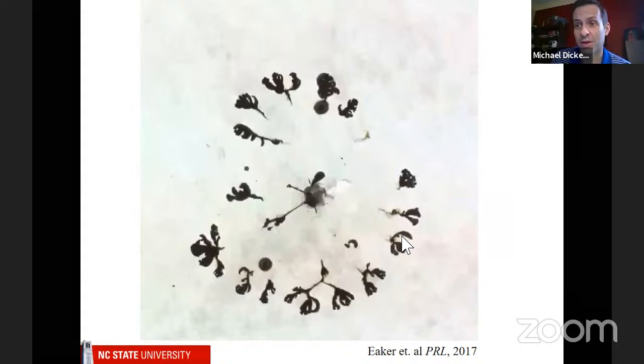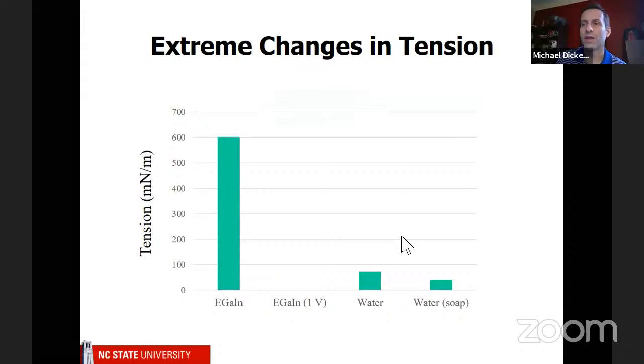So the implication here is we're lowering the surface tension very, very low. And to give you an appreciation for this, because again, I don't think most students think about surface tension, because it's something that's really only important at small length scales. So this is a plot of surface tension for different materials. Over here you have water, which remember is about 72. And if you apply soap to it, it goes down to about 40. So that's maybe a factor of 2 change. And over here we've got the liquid metal, which is between 500 and 700, depending on the environment it's in. And when we apply 1 volt, it's basically 0. So if these numbers don't mean something to you, let me actually show you a slide I use with American audiences, so I'm sorry that I don't have any kilograms.